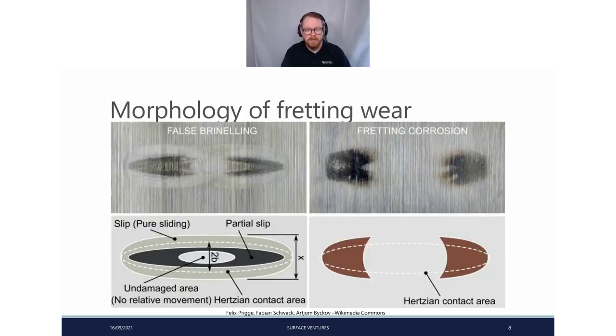Thank you. Okay, so getting back into this, the morphology of fretting wear. What does one of these wear scars look like? What we have here is a fairly typical fretting wear scar. The first is a little more wear driven, whereas in the second the load is not quite so severe, and we have more of a fretting corrosion, essentially fretting oxidation, type of scenario. So in the first one, the one on the left, we have false brinelling, what appears to be a false physical deformation of the surface.